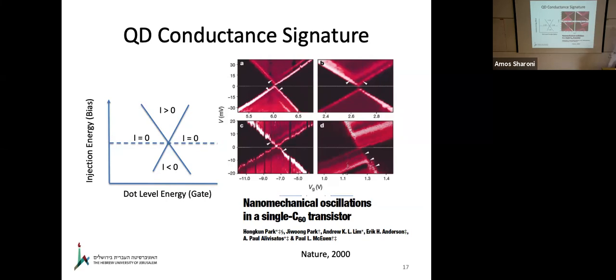Well, okay, so you're right, but there's 50 years of know-how of people who work with these quantum dots. For example, people who work with gallium arsenide have developed working methods of how to cool down the dots in such a way as to quench away a lot of the dirt. And if you work in gallium arsenide, it's a very, very clean system. With molecular physics, it's much more complicated because they have a single molecule, which is indeed a very, very dirty environment. And I'm going to show also that with defects, the environment is actually pretty clean because it's a single defect where there's not much around it.